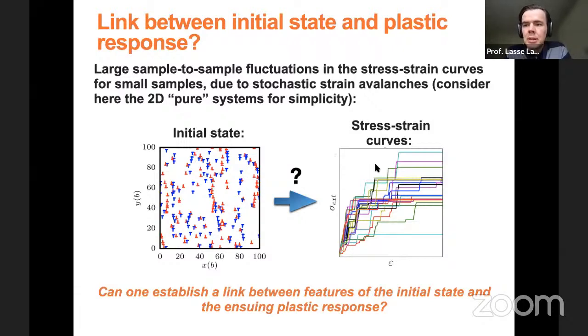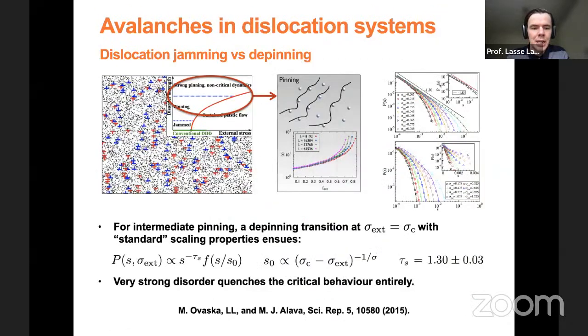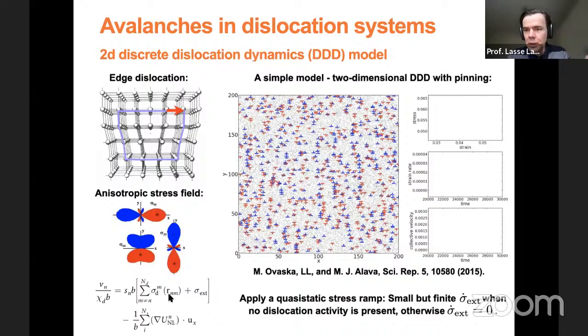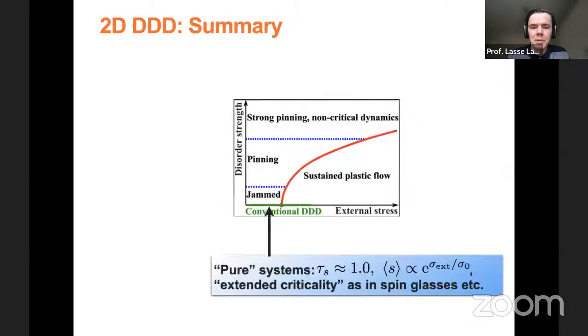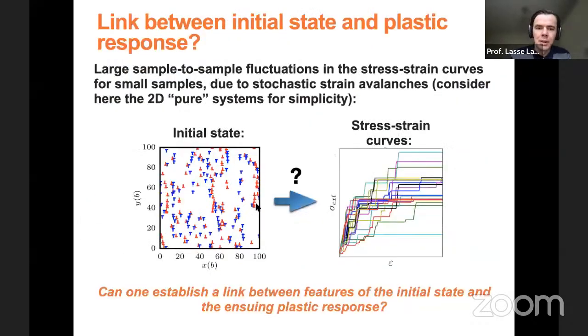Of course, now this is a subtle point because you could argue that, okay, this is a deterministic system. So if I know exactly where my dislocations are in this initial state, then I can construct a model which would be basically equivalent to these equations of motion here, which are deterministic. So I should exactly be able to find a mapping from this initial state to the stress strain curve because it's a deterministic system. However, in practice, it's more complicated than that because you have this complex dynamics going on. So you have these avalanches, critical-like avalanches that are often understood to be inherently unpredictable. So it's the kind of dynamic process that you are always on the verge of stopping, but then you might still keep going for a long time, for instance. So it's a very sensitive thing.